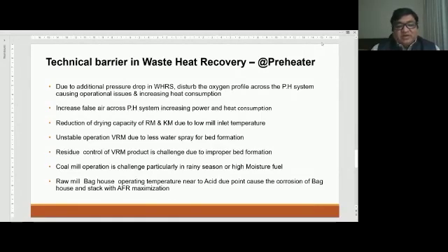In some cases we also noticed, because in most of our Indian cement plants the raw mill grinding is the VRM, as we all know that a VRM needs a stable bed formation to avoid vibration as well as tripping of the mill, which needs water. So when you put more water in the mill, your hot gases coming out from the waste heat recovery system are already at a low temperature. Your product as well as the mill operations become very unstable or critical to operate, which impacts your residue as well as your mill performance because of the poor bed formation under the table.